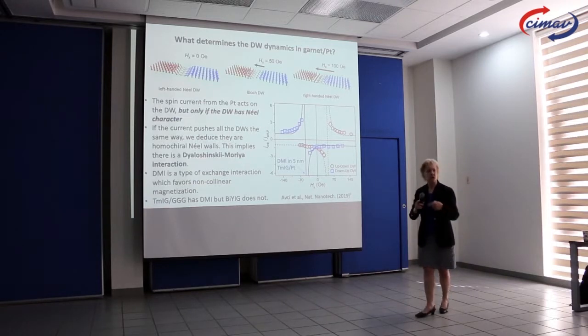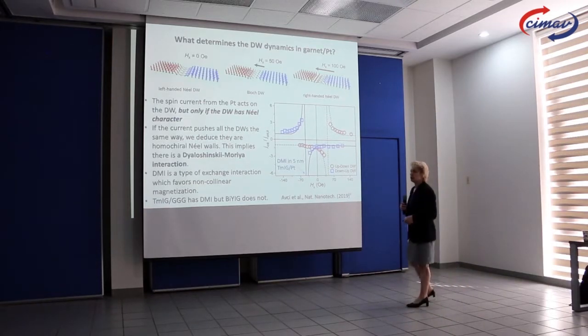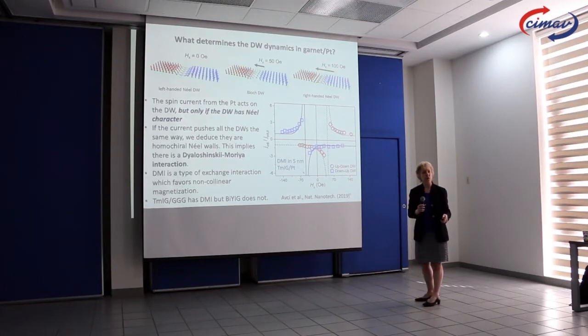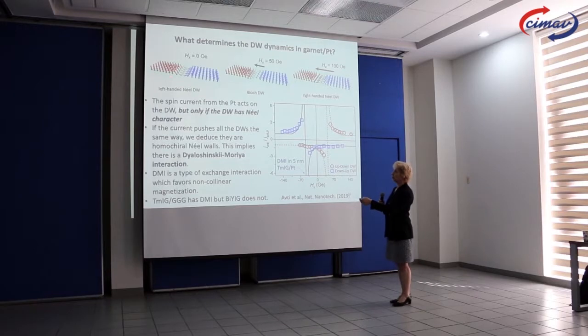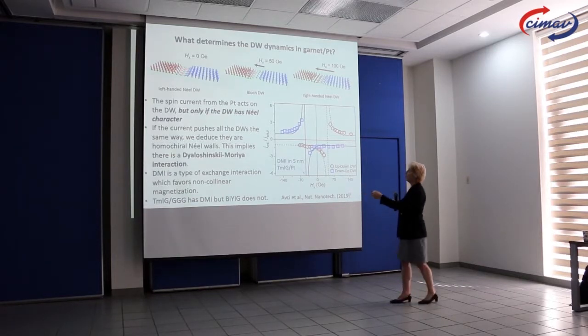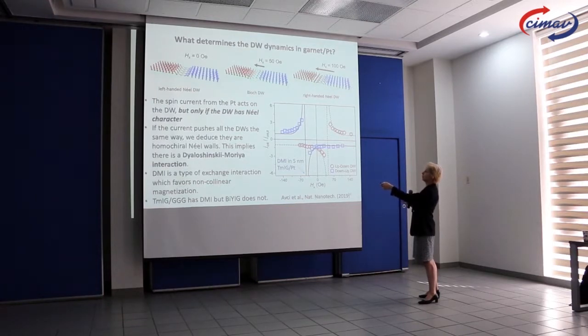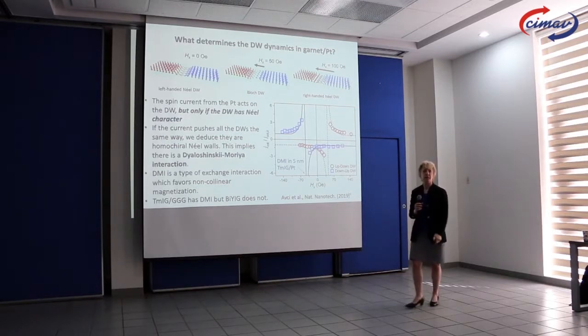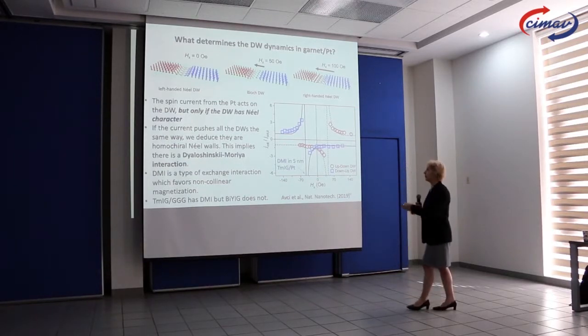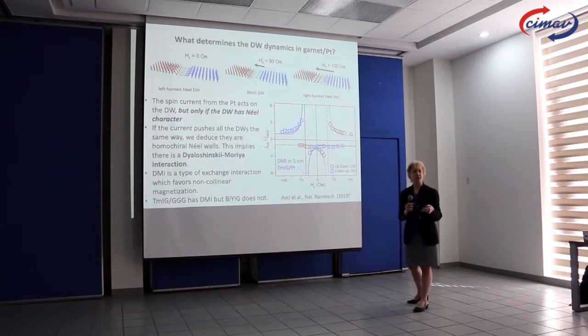And so this is a little involved, but I'll try and explain it in a straightforward manner. It all depends on what kind of domain walls are present. So if you look at a domain wall in a film with a perpendicular anisotropy, the domain wall can be a Néel-type domain wall, where the magnetization is going from down to up via this direction, which is perpendicular to the plane of the domain wall, or it can go via a Bloch wall, where the magnetization rotates so that it's parallel to the domain wall at the center of the domain wall. And by the geometry of these devices, this doesn't actually give you any domain wall velocity if you apply a current in the platinum. These are the only ones that work. So you have to have this kind of domain wall.